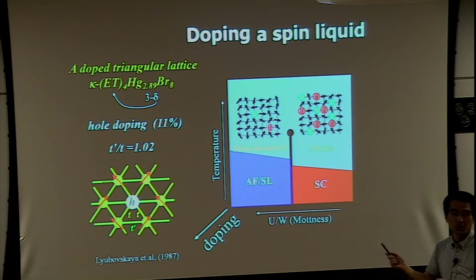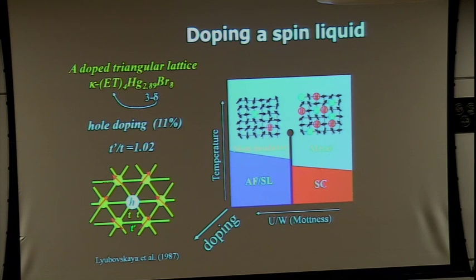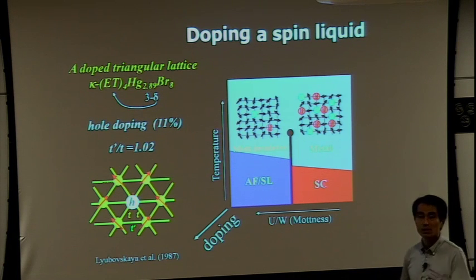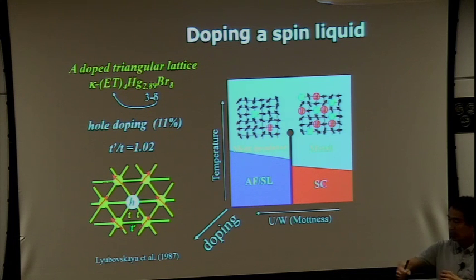This has a very good reason, because mercury is a very, very strange element, and in compounds, mercury often forms its own periodicity incommensurate with the hosting lattice. And such a situation occurs. So this missing content, for example 0.11, is not a defect. Mercury forms an incommensurate superlattice in the insulating layers. So this missing content serves as hole doping. So 11% hole doped in the Mott insulating layers. And okay, so we have a spin liquid insulator and an 11% hole doped Mott insulator.